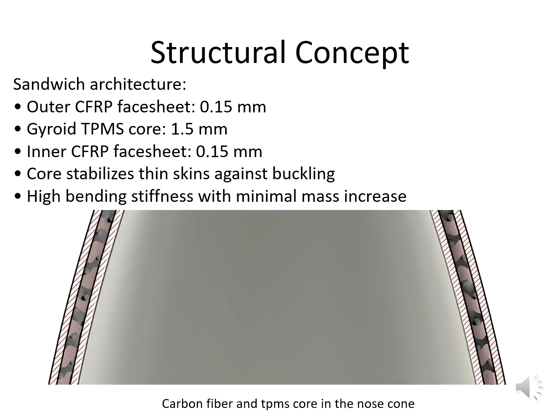The structural architecture is a classic sandwich construction adapted for small-scale aerospace components. We use two 0.15 mm carbon fiber skins, which provide most of the bending and in-plane stiffness. Between them we incorporate a 1.5 mm gyroid TPMS core. Gyroid lattices are extremely efficient because they feature continuous curvature and uniform load paths, unlike random infill or honeycomb structures.